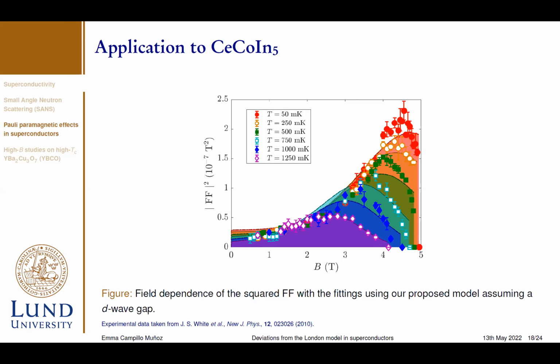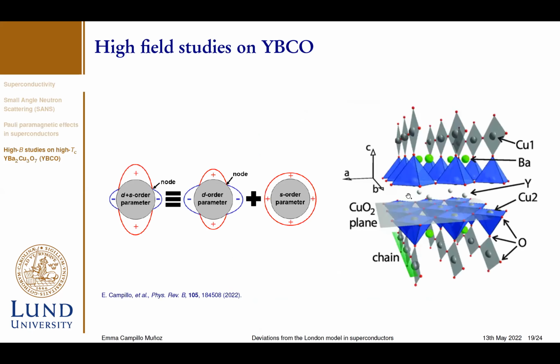Then, following the trend of studying other unconventional superconductors, we continued our research studying another really well-known high Tc superconductor, which is YBCO. The particularity about YBCO is not only that it's high Tc, it's also that the superconductivity is developed in two directions. We have copper oxygen planes in the AB direction, which are thought to develop D wave superconductivity, and also we have superconducting chains of copper oxygen in the B direction, which have been suggested to carry S wave superconductivity.